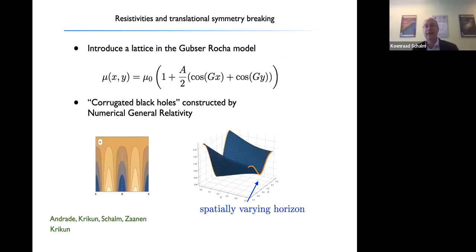And the new ingredient that we brought to bear on this is we have introduced a lattice, an ionic lattice in the system, where we have the chemical potential not as a constant throughout, but it undulates. It has a modulated behavior in both the x and the y direction with an amplitude A and a lattice wave vector G. And then we compute the background solution of this, the ground state, the finite temperature state of this system through numerical general relativity.